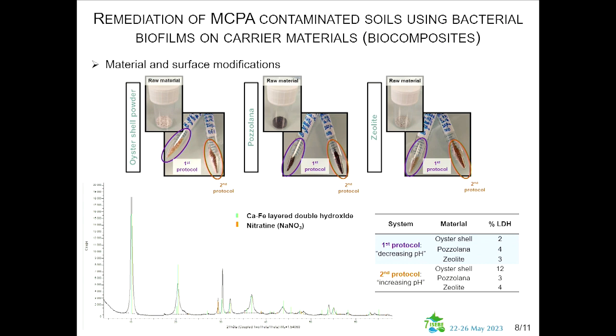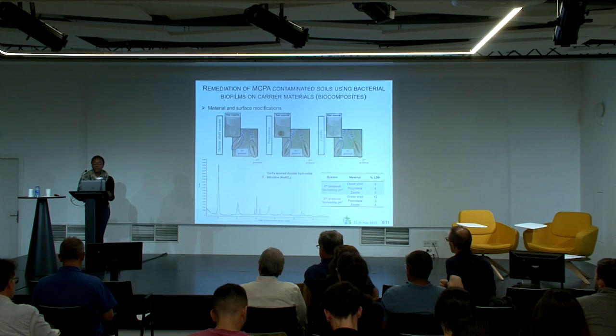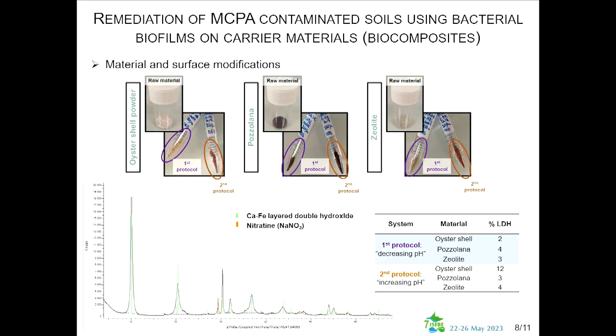I said that we have to do so to be able to check that we formed layered double hydroxides and not other things, like can happen if the mix of the sodium hydroxide and the calcium and iron solutions is not made at the appropriate flow rate. We can, for instance, only form ferrihydrite, which is a simple iron oxide and not a layered double hydroxide. So we have to check the nature of this phase before any other experimentation. And this succeeds. We form layered double hydroxides, with a covering rate of about 3–4%, except in the second protocol for the oyster shell.